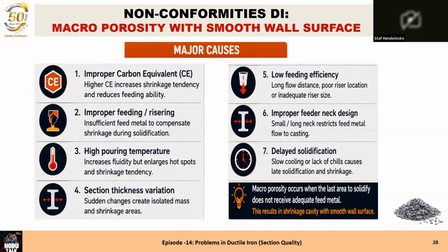Sometimes we need chills, because a chill is a tool that will increase the feeding length of a riser. A chill never compensates a shrinkage or a porosity. It increases the feeding length of the riser, and therefore, especially in thicker castings, let's say from 30-50 millimeters wall thickness on, it can be very interesting to use chills for decreasing the number of risers you will have to put.